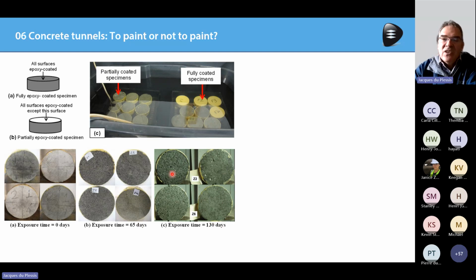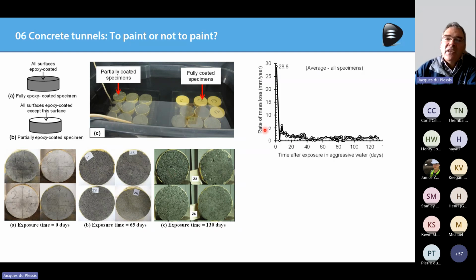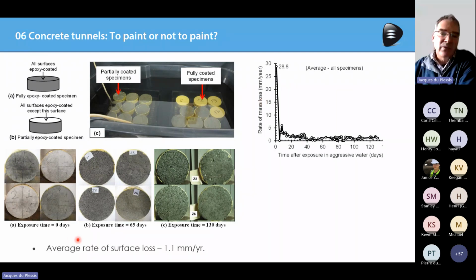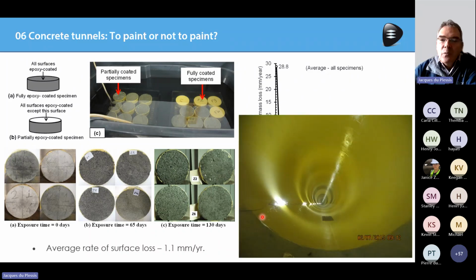So based on this, the rate of mass loss of the concrete was determined, because you could weigh these samples, and based on that, the average rate of surface loss was estimated to be 1.1 millimeter per year. So 11 millimeters in 10 years. And based on these results, it was decided to paint the tunnels. So a very interesting exercise that was done on site.